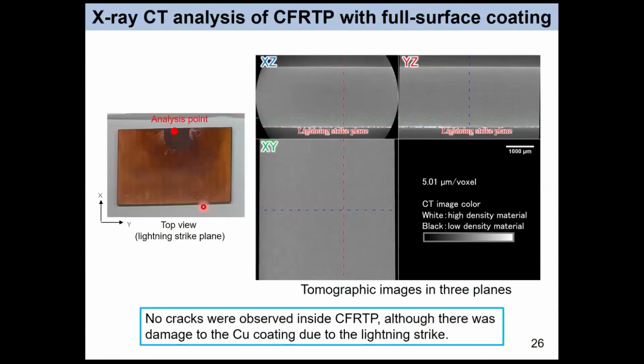And this is the result of the cold spray samples with full surface coating. In this case also, we cannot see damage inside the CFRTP, no darker color, and no crack or delamination in this picture. So no cracks were observed inside CFRTP. This full surface coating can effectively reduce the damage to CFRTP.